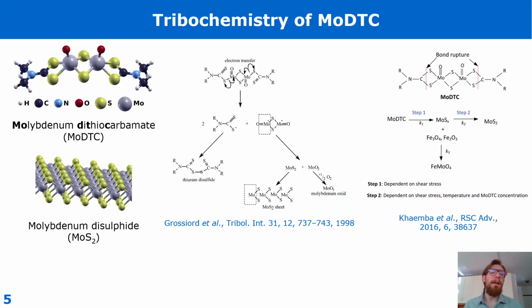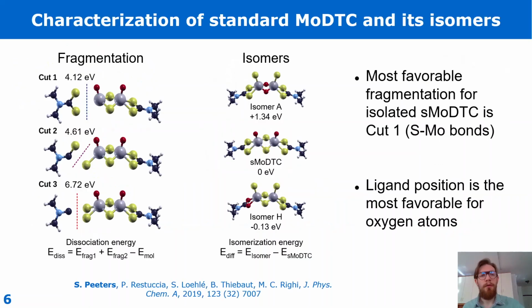However, the complexity of MoDTC relies not only on the decomposition mechanism, but also on the quick oxidation that these complexes undergo. So we started our investigation by considering different fragmentation patterns of MoDTC compounds. As you can see, for the isolated compound, the easiest way to break the molecule is between sulfur and molybdenum, because it has the lowest fragmentation energy.